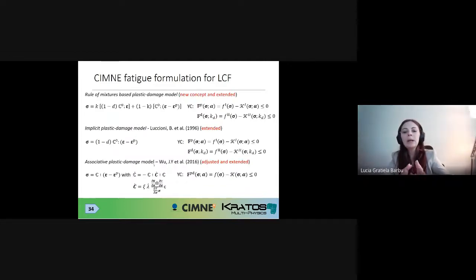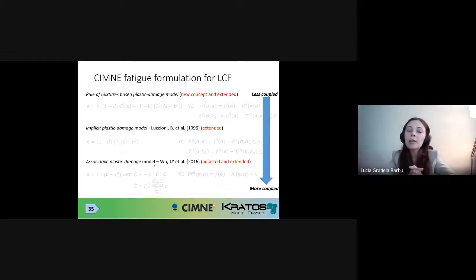Okay, now, if you are looking at these 3 different plastic damage models, I've arranged them a bit different and you will understand very soon why. Basically, because I want to show to you there is a transition in between a less coupled behavior to a more coupled behavior. What do I mean with less coupled behavior? For instance, the rule of mixture based plastic damage model can allow 2 different surfaces, one for plasticity and one for damage, which behave in a completely different way. The implicit plastic damage model by Luccioni allows 2 different surfaces, but if they are moving in 2 different ways, you're losing convergence, you have instability in this model.